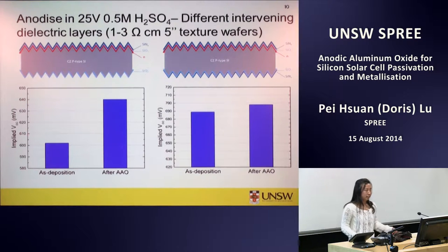Further moving to the 5-inch commercial wafer, 1 to 3 ohm-centimeter 5-inch textured wafer. There's a roughly 40 millivolt increment when anodizing a layer of aluminium on top of 10 to 15 nanometers of thermal silicon dioxide. And for the silicon nitride structure, after annealing, the average implied VOC of a 5-inch wafer is 690 millivolt. There's another 6 to 8 millivolt improvement on top after anodization, even on the annealed wafer.